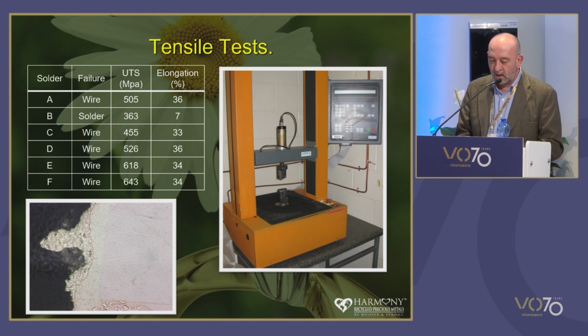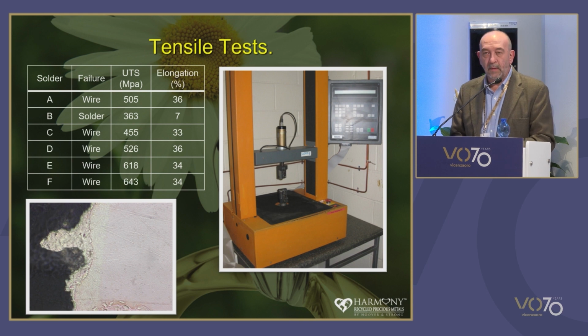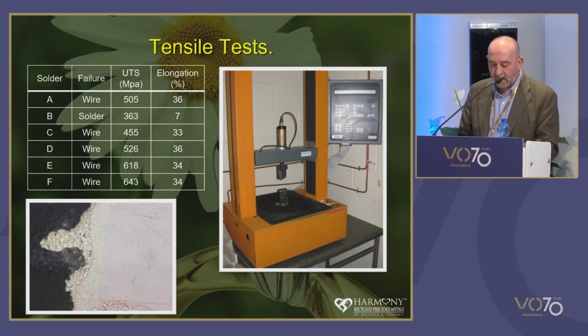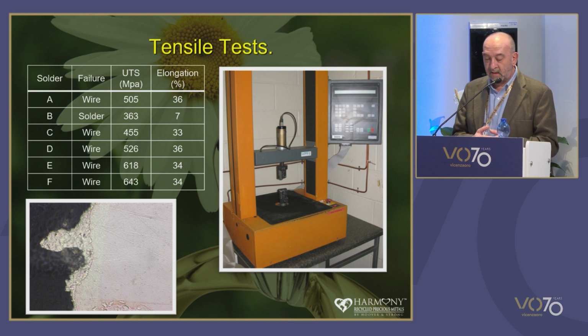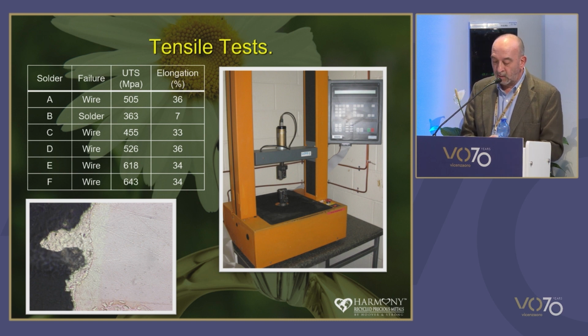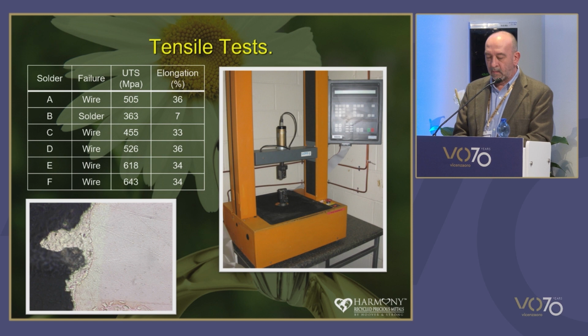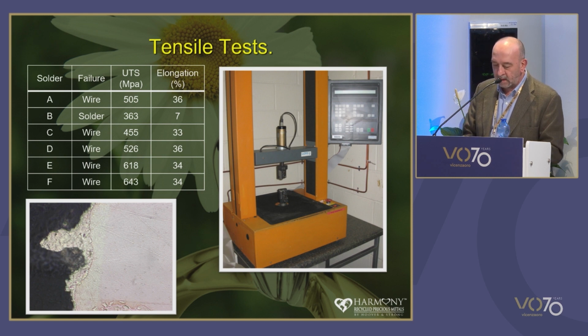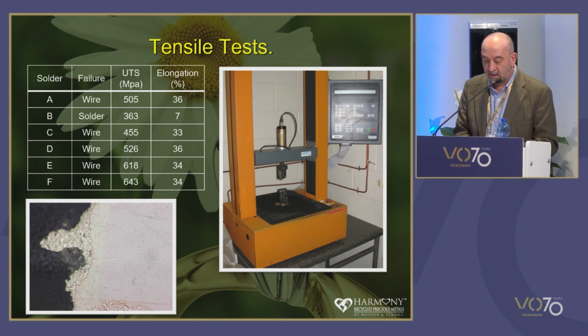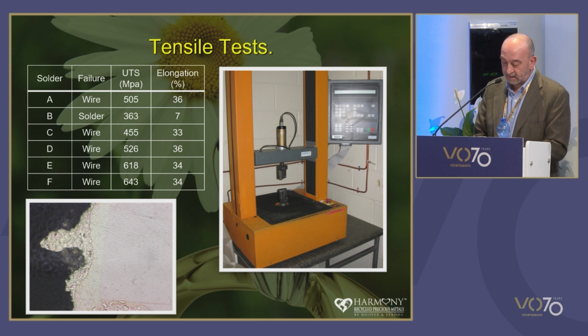And the results here show that only one sample failed at the solder joint, and it was again solder B. And looking at the marker section there on the left, we can see that the failure was through the solder and not at the interface, suggesting the mechanical properties of the solder were the problem here. The tensile strength that was recorded at 363 megapascals, or newtons per millimeter squared, is adequate for most jewelry applications, so there's not necessarily any need to worry about this. It's just not as good as the others in the test.